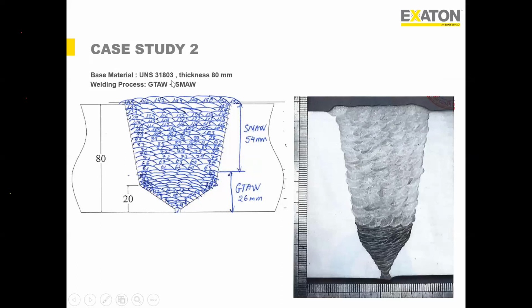The base material is a duplex, and imagine a thickness of 80 millimeter. It is a huge thickness material. It was a pipe to flange welding. You can see here the welding was done 20 millimeter with TIG and 54, I'll tell you, there are quite interesting stories there. It was supposed to be done 54 millimeter with the SMAW process. The challenge in this particular grade of welding was the grinding. Initially we thought we would go for only the root pass with a super duplex TIG rod to protect the root, followed by the SMAW process.